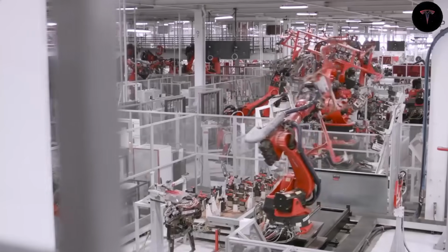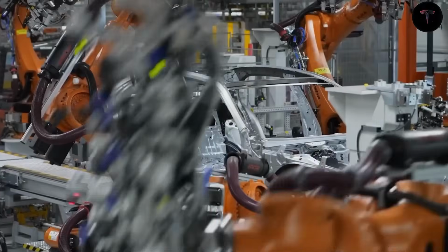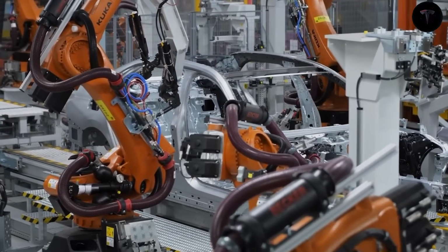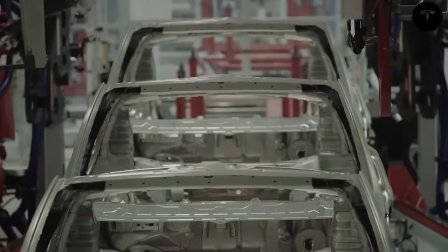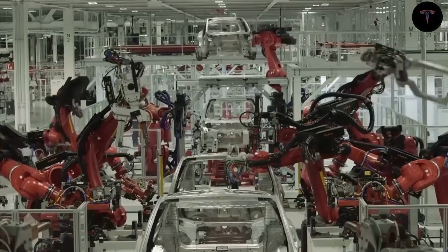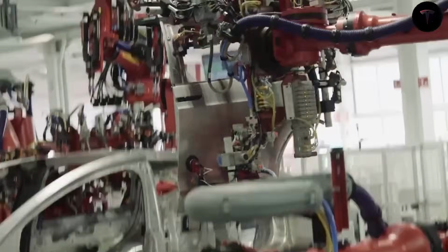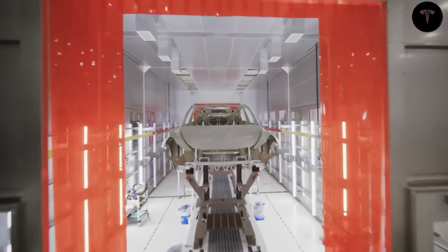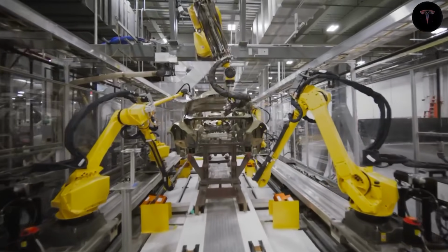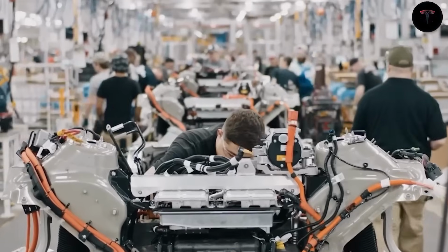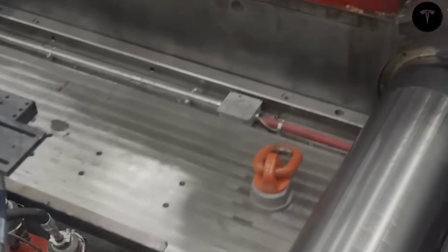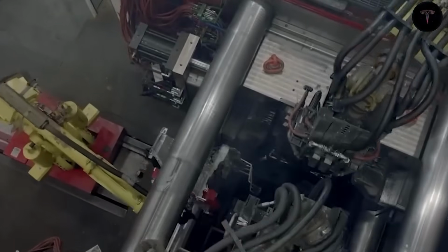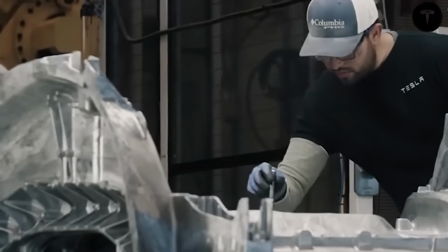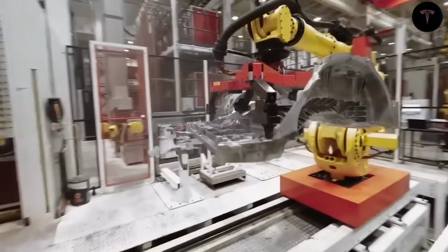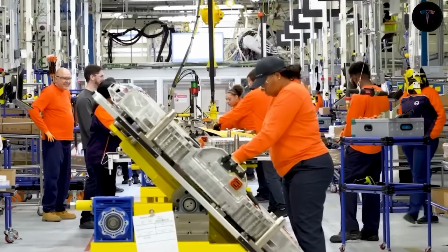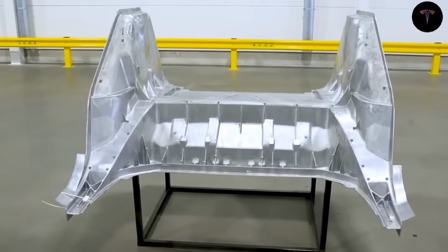The science behind the casting process is as impressive as the machine's scale. It begins with aluminum, a blend of pure aluminum and recycled material from previous castings, melted in a natural gas furnace at approximately 850 degrees Celsius. The new system uses a dual furnace setup. The primary furnace handles initial melting, while a secondary electric holding furnace maintains the molten metal at a stable temperature between 750 and 850 degrees Celsius with high precision.